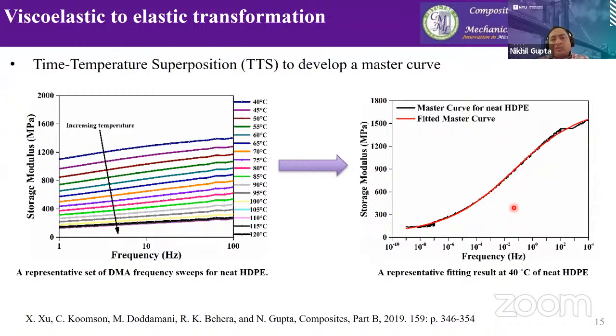And what the master curves give us is the data from 10 to the power minus 10 to about, actually it goes much wider, it goes to about 10 to the power 6. But we are cutting it off here because data is not reliable after these ranges. 10 to the power minus 10 is already extremely slow, and 10 to the power 4 is where we need to capture additional transition temperatures. So that's why this range is selected here. So once we select these curves, then we can fit an equation on top of it to estimate this. And this equation will be useful for us. We call it a master curve.